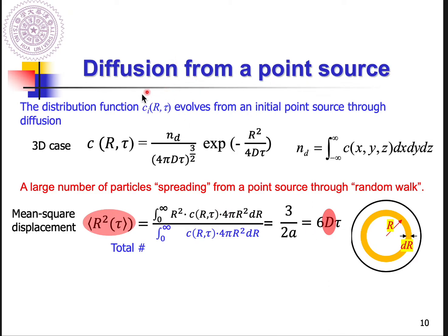This case is diffusion from a point source, right? And if the diffusion is not three-dimensional but one-dimensional, for example, the point source diffusing into a one-dimensional narrow wire, then you need to modify the concentration profile with this one, and this term should be modified as dr, because it's a narrow wire. dr is a length.